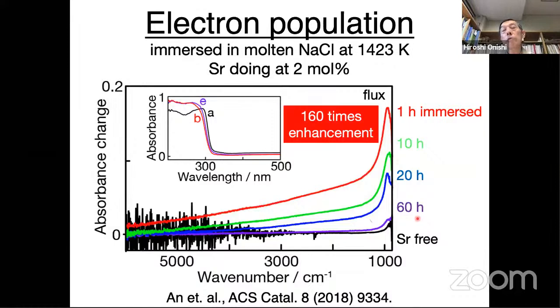I hope you remember that strong infrared absorption indicated a large number of electrons are available in the photocatalyst. So we found the 1 hour heated sample presented the largest number of electrons. And by heating for a long time, for 60 hours, the number of electrons went down. So we found the number of electrons were very sensitive to the heating time. And the short heating time was good to increase the electron number.